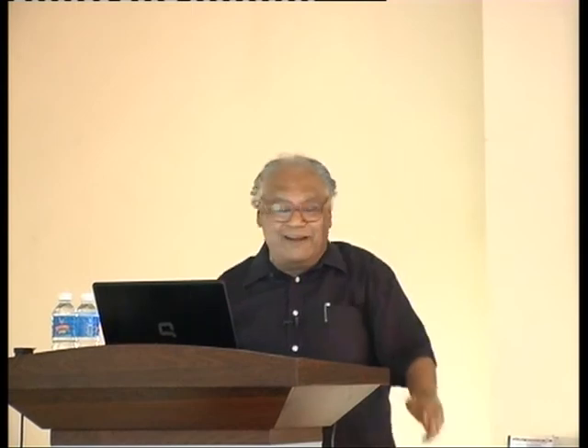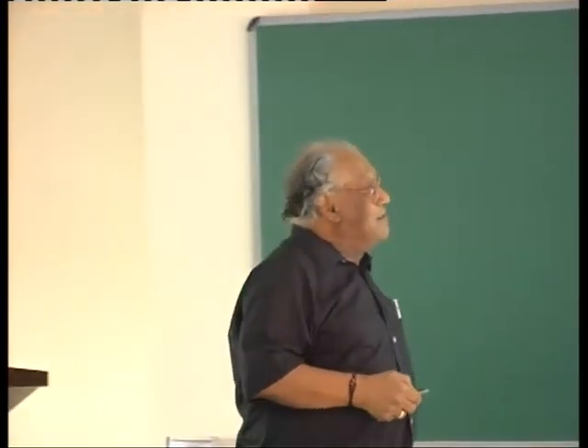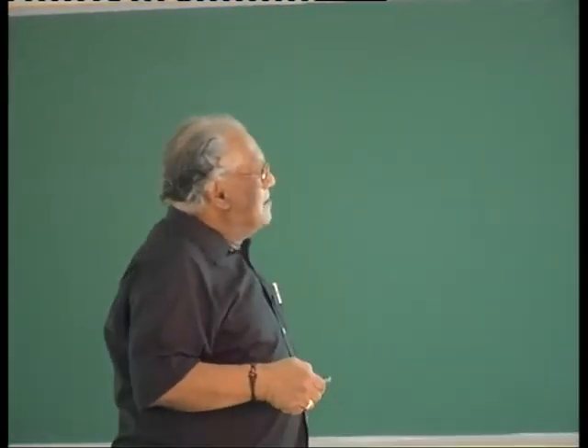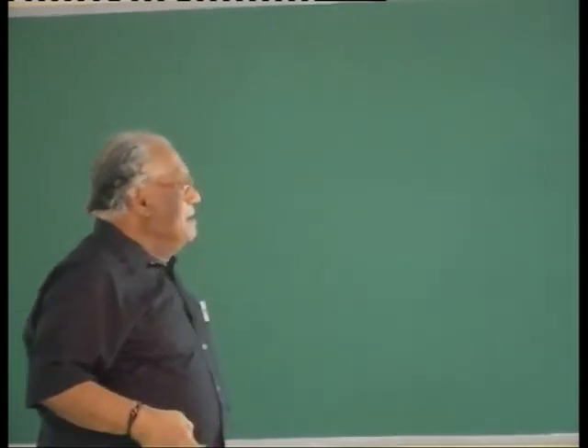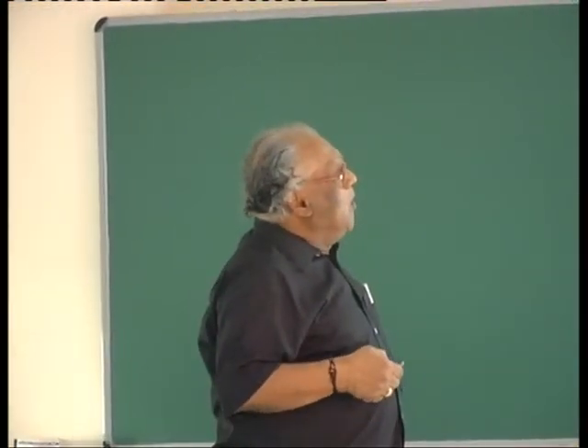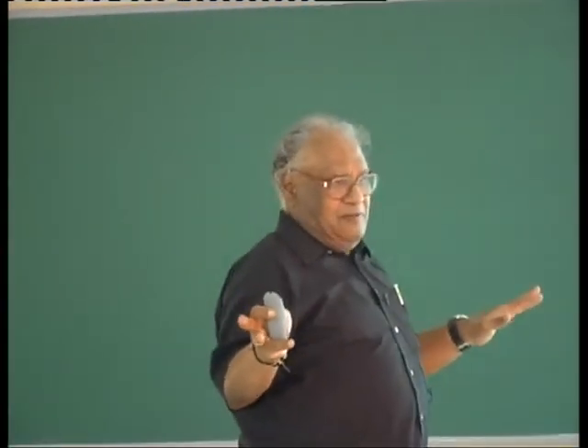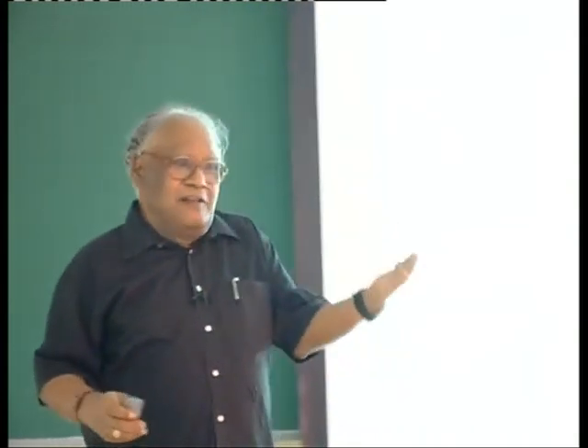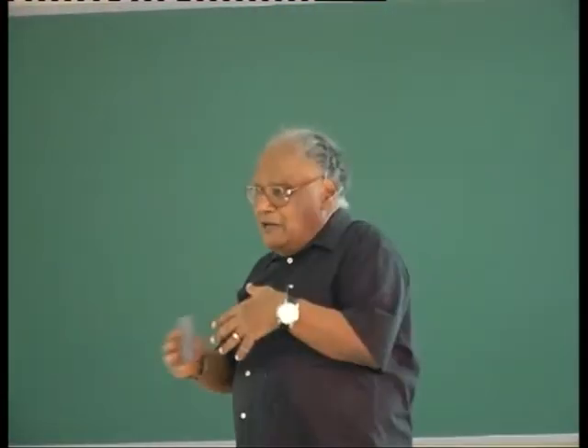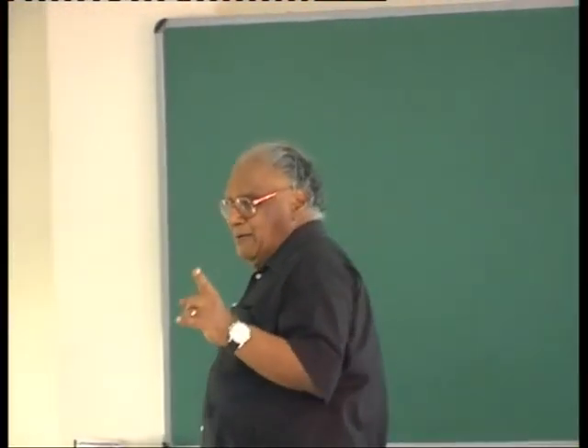Okay, I will close this talk by showing ferromagnetism. The occurrence of ferromagnetism and ferroelectricity need not be only in these materials but also in nanomaterials. One of the things that has come out of Bangalore from Nehru Center, mainly the work of Sundaresan, is that all nanoparticles are ferromagnetic because of the surface. That is now a universal rule. Doesn't matter which material you take, whether magnesium oxide or aluminum oxide, you don't need a magnetic ion. It will be ferromagnetic because of surface ferromagnetism, because of defects and so on.